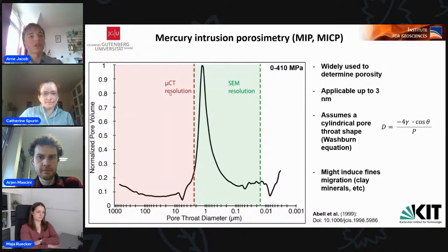But when the pore throat geometry becomes too complex, this might lead to an underestimation of larger pores, while smaller pores are overestimated. At this point, I'd like to recommend the work of Abel, who replaced mercury with Wood's metal and showed how large this effect can be. Well, in our case, this meant we only knew that we had a very complex pore structure, and we have a lot of porosity, which we cannot see in the CT images.